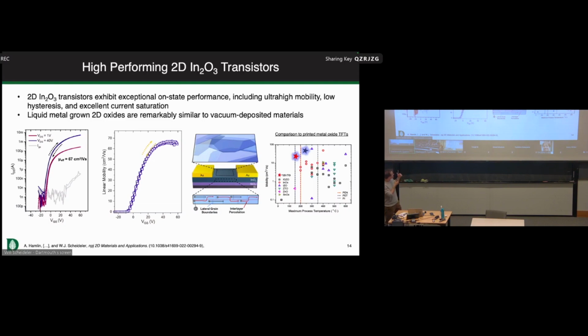And that tells us that our material at least has some of the properties one might need if you were going to design flexible circuits, thin film electronics based on this. If we benchmark it against other related materials, for example, from the chemistries that I mentioned earlier, it's approximately an order of magnitude better at the temperature range that we need to put electronics on flexible polymers.